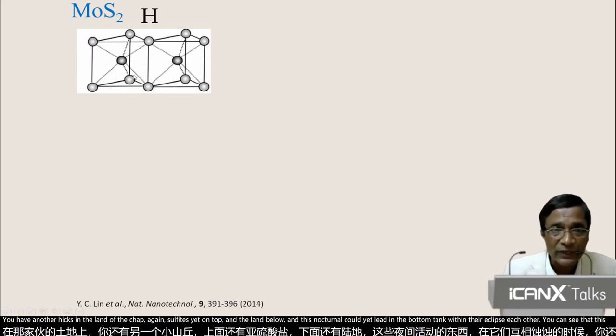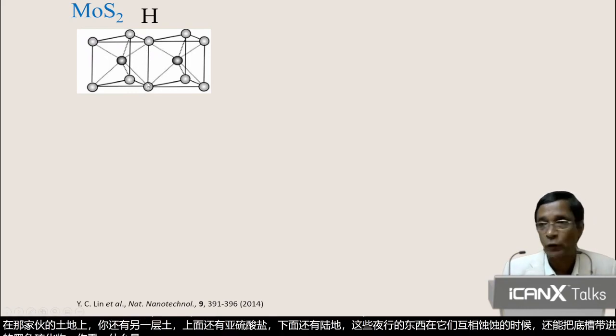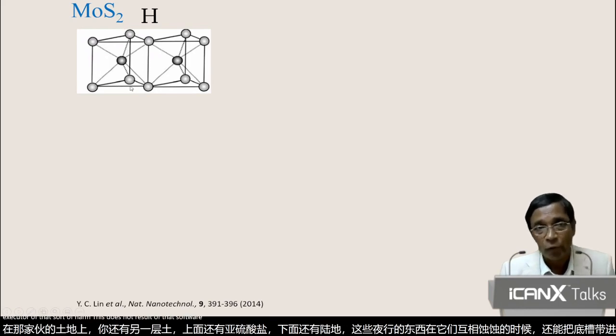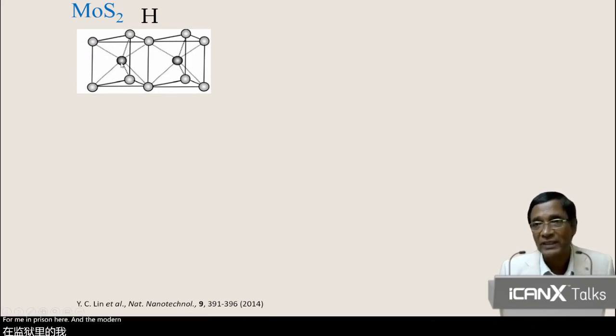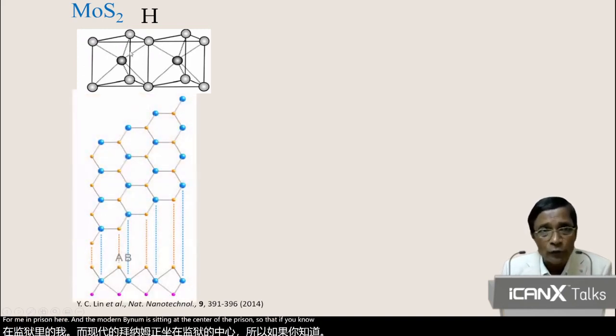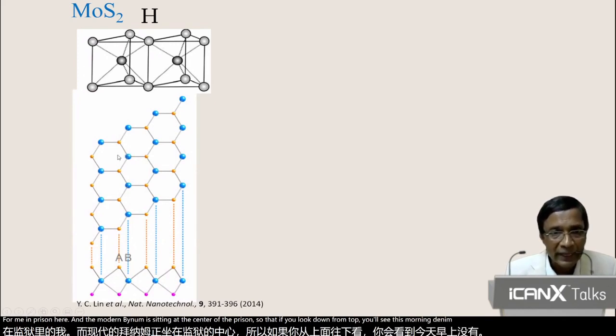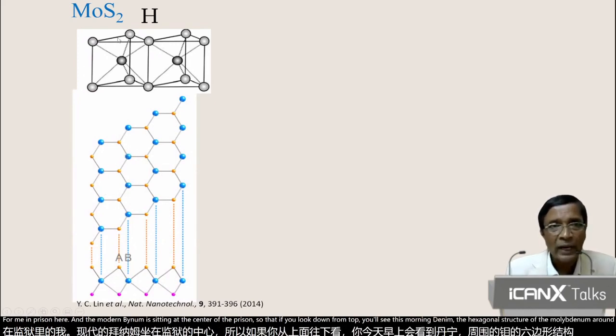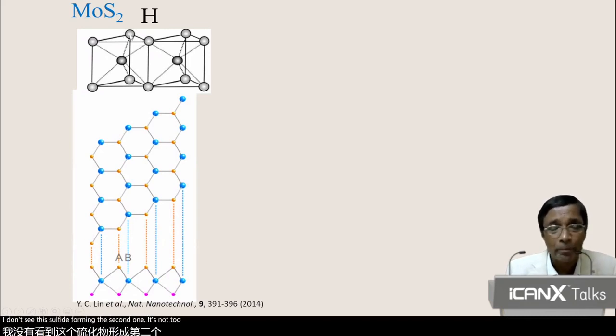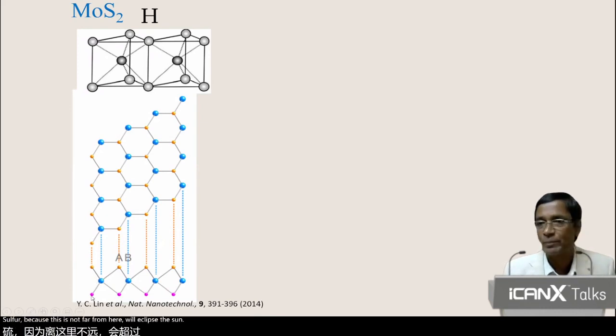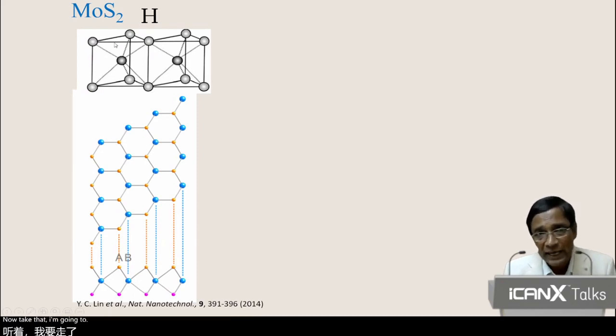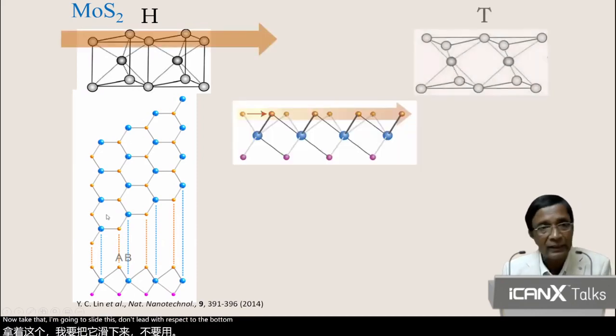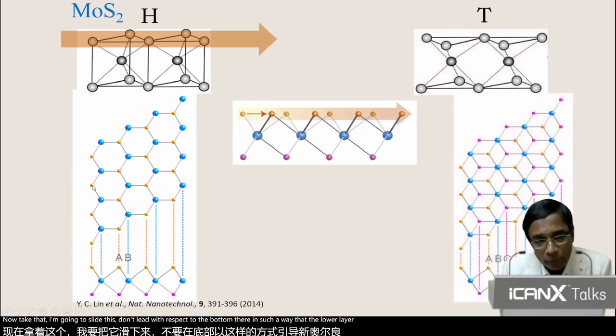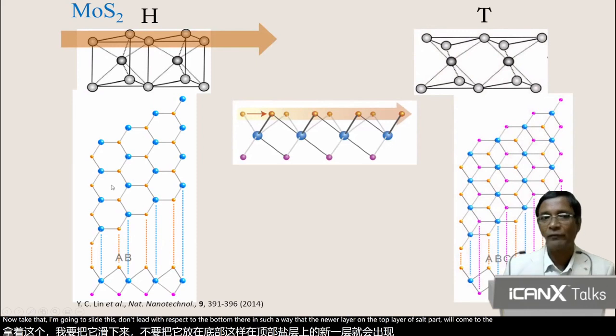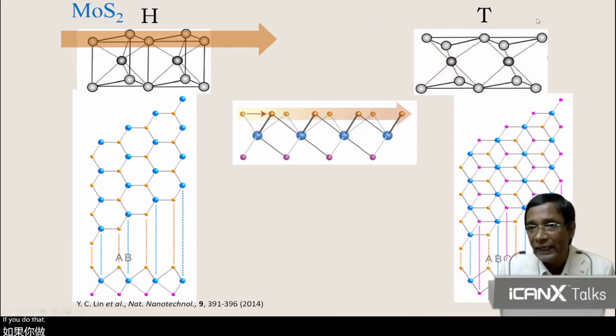You can see that this sulfur is exactly on top of that sulfur, this sulfur is exactly on top of that sulfur, this sulfur is on top of that sulfur, forming a prism here. And the molybdenum is sitting at the center of the prism, so that if you look down from top, you will see this molybdenum, the hexagonal structure of the molybdenum around it, and you will see this sulfur forming the hexagonal structure, but you will not see this sulfur because this sulfur here will eclipse the sulfur that's below. Now think that I'm going to slide this top layer with respect to the bottom layer in such a way that the top layer of sulfur will come to the center of this hexagon. If you do that, then you form this structure.